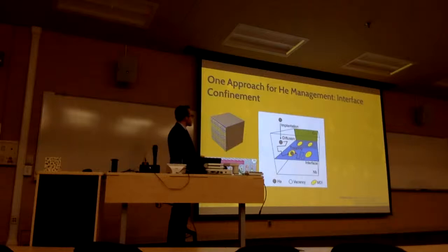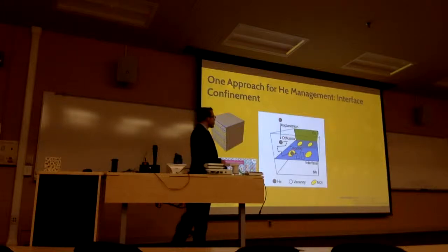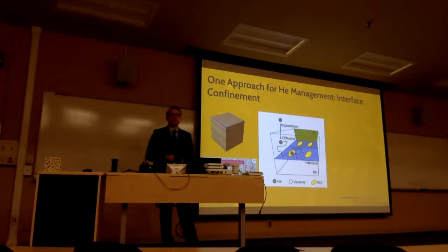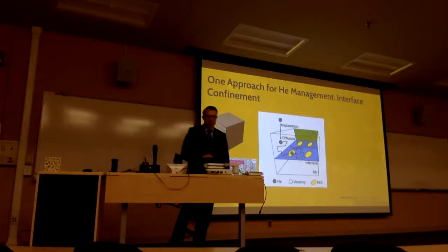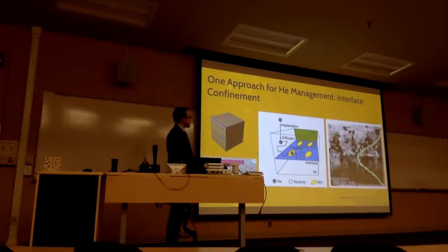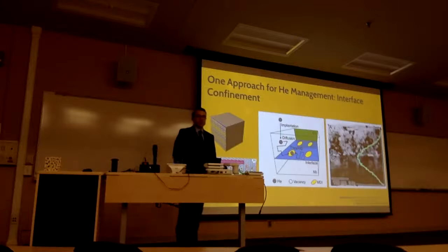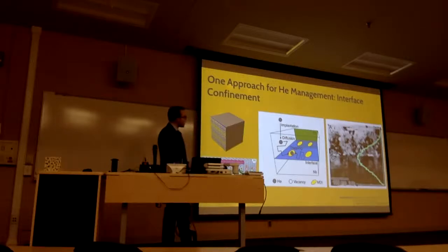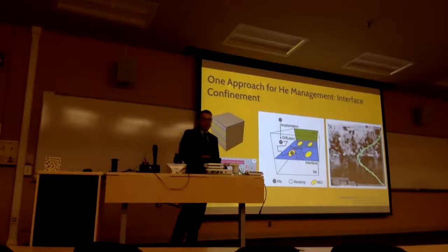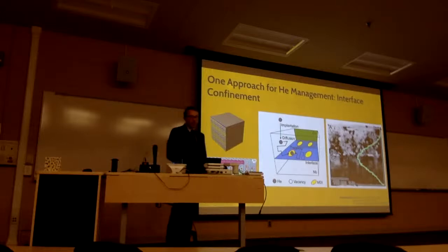We can actually see this simulated model where we implant helium inside the sample. It diffuses to the interface, and those misfit dislocations act as traps between those two layers. We've actually seen this experimentally. This is a copper niobium multilayer. You can see the development of helium bubbles inside the sample due to helium production. And this green plot measures the density or the accumulation of helium across the thickness of the sample. You can see that the helium density is much greater at the interface as opposed to the thickness of each of those layers.